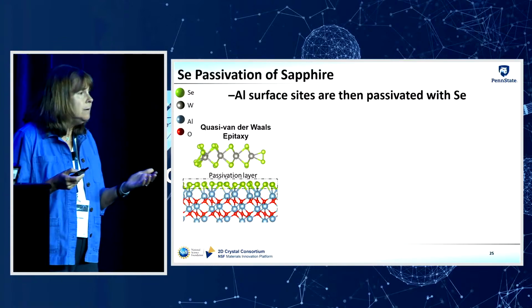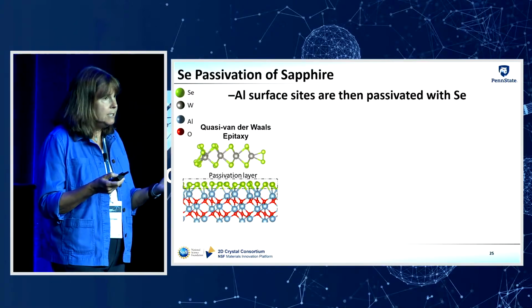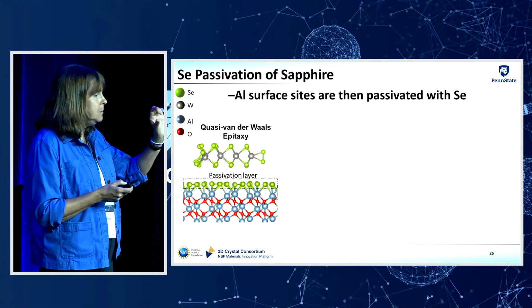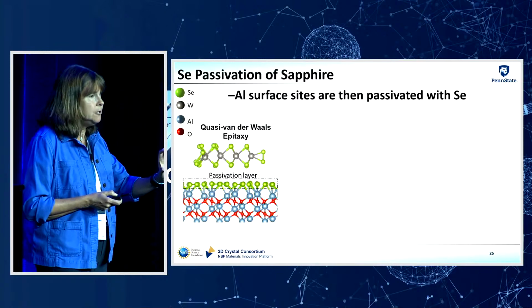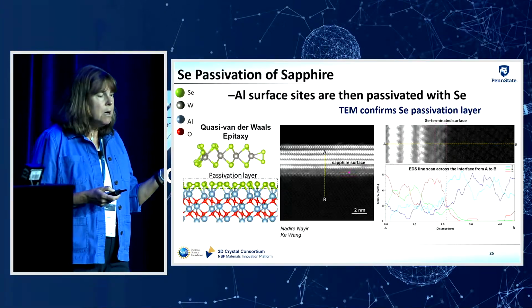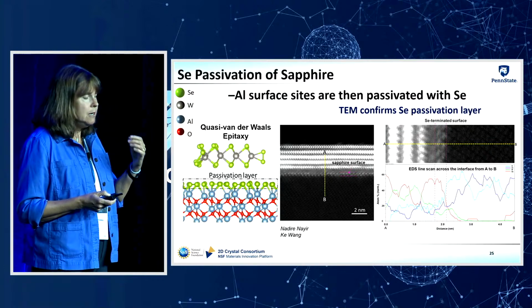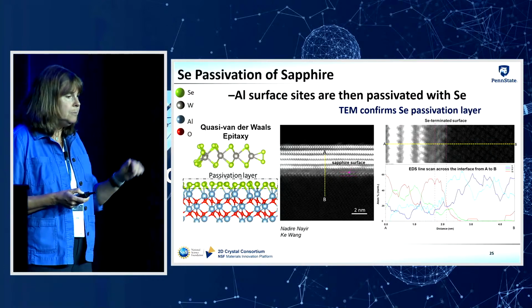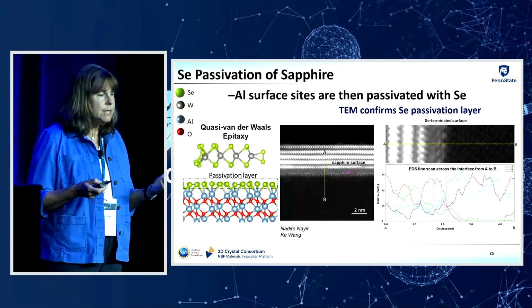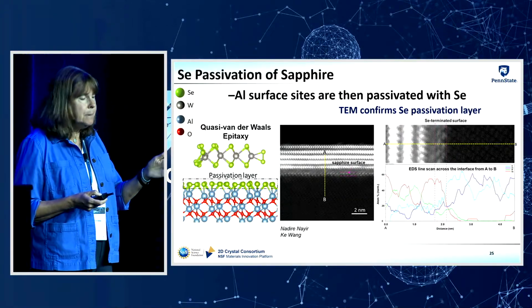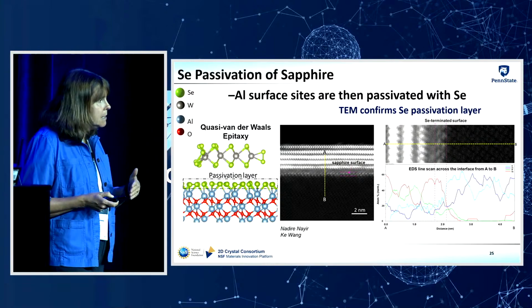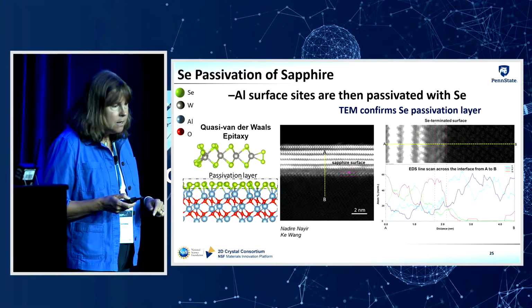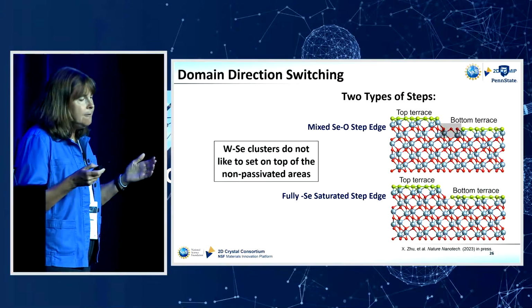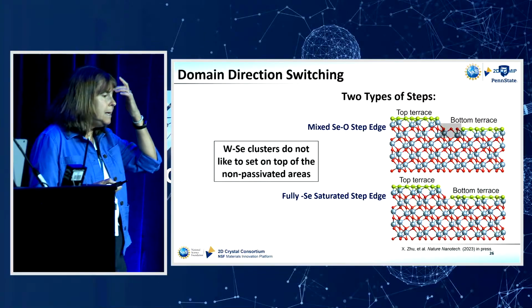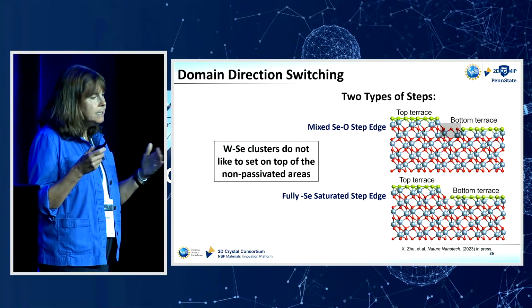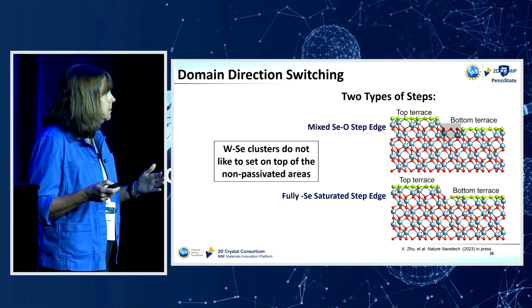And that's actually an important thing if we have van der Waals epitaxy occurring, if we don't have chemical bonding between our 2D film and the sapphire surface. So we assume in this model that we have selenium passivation of the sapphire surface when we have an aluminum terminated surface. And we have evidence for this selenium passivation layer experimentally from cross-section STEM imaging and EDS that I'm showing here. So in the model, they're assuming that when we have aluminum termination, the surface is going to become passivated. And so they can consider two different types of steps that we might have.